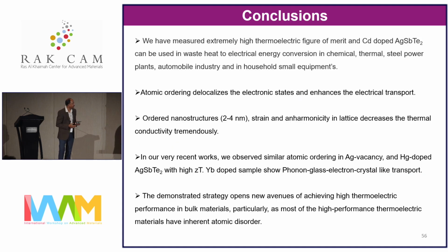So we have measured extremely high thermoelectric figure of merit in AgSbTe2 systems by partially ordering the atoms. Partially ordering the atoms actually delocalizes the electronic states, and partial ordering can create nanostructures which are the size of the mean free path of the acoustic phonons in those compounds.